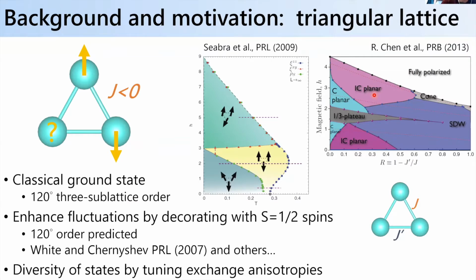And so for those of you who haven't thought about this before, if I was to decorate a triangular lattice with antiferromagnetically aligned spins, then there's this obvious scenario that comes up where I can't decorate the entire triangle with anti-parallel spins, right? There's always going to be one site that's frustrated relative to the other 2. And so classically, we know that nature solves this problem by acquiring what we call a 120-degree ground state, where each spin is rotated 120 degrees relative to its neighbor across the triangle. And so this is the classical ground state for Heisenberg moments on a triangular lattice.